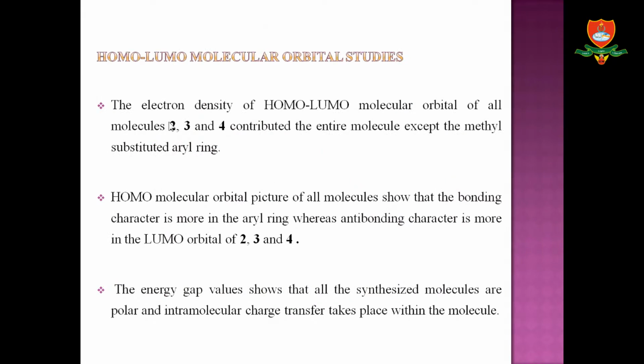From that, the electron density of the HOMO-LUMO molecular orbitals of molecules 2, 3, and 4 is distributed over the entire molecule except the methyl substituted aryl ring. The HOMO molecular orbital picture of all molecules shows that the bonding character is more in the aryl ring, whereas the anti-bonding character is more in the LUMO orbital of 2, 3, and 4. The energy gap value shows that all the synthesized molecules are polar and intramolecular charge transfer takes place within the molecule.